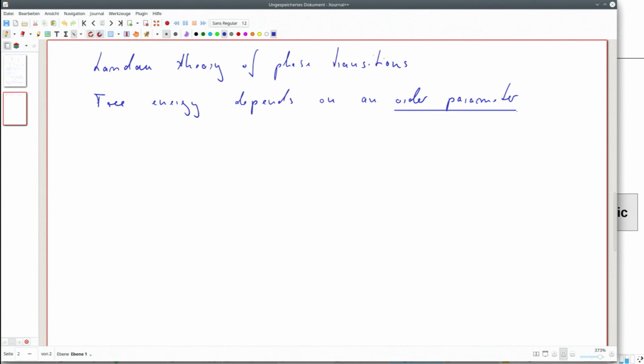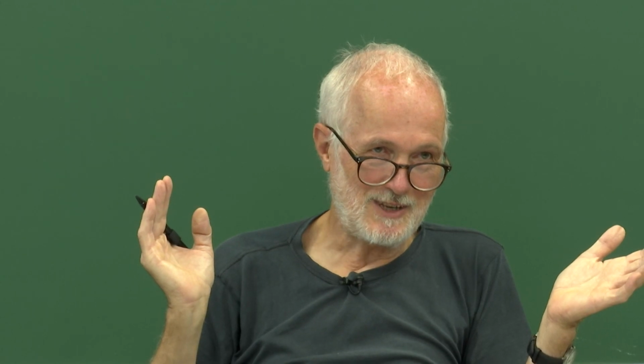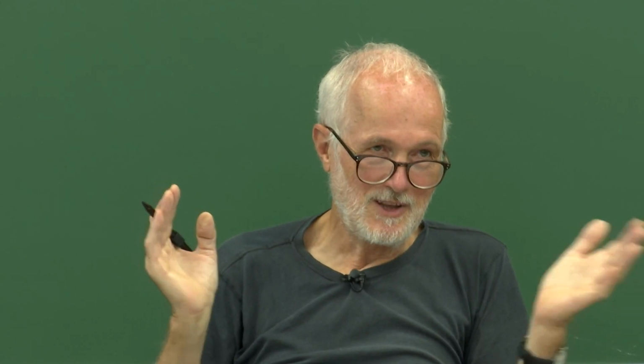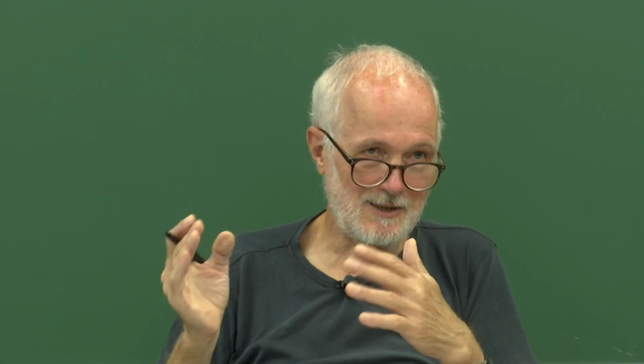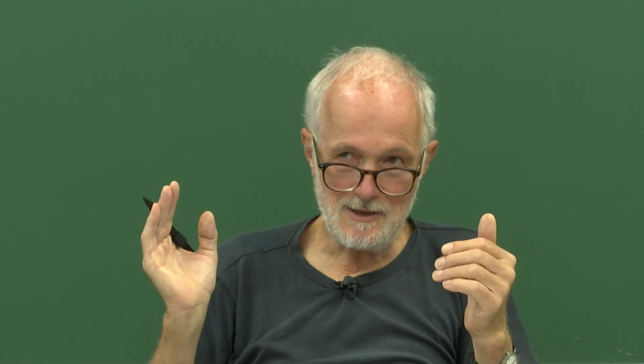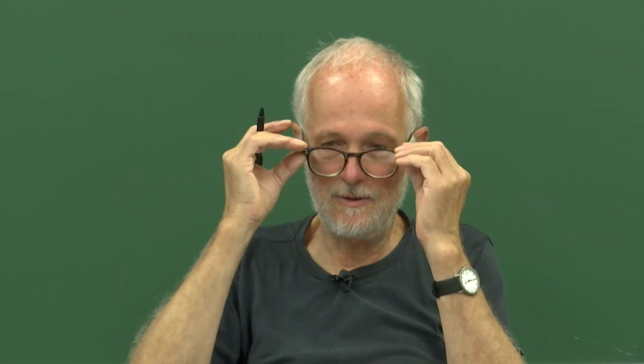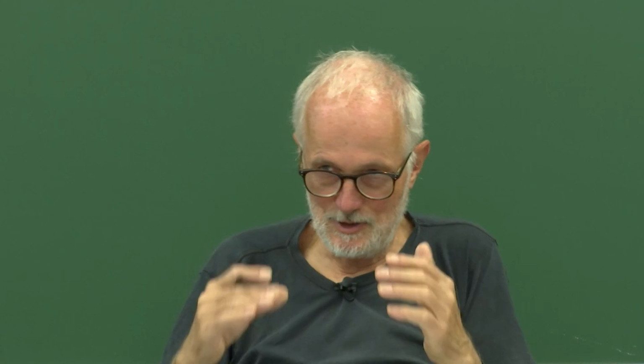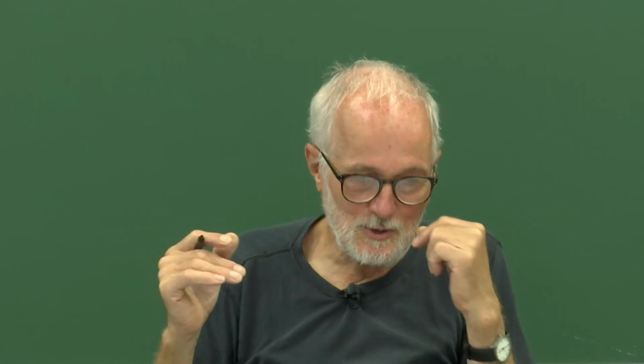For this simple example of ordering phase transitions, where some species enrich on one sublattice, it's very simple what we define as the order parameter. For other transitions, it's far less obvious. For this gas-liquid transition, it's just the density which is used as an order parameter. For a superconductor, it's a density of Cooper pairs. For a magnetic system, it's a magnetization, and so on. So with some effort, you find such an order parameter which characterizes the degree of order.